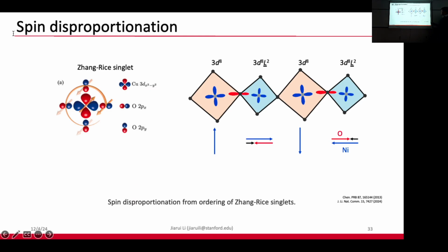So we try to recall a very old concept in cuprates called Zhang-Rice singlets. This is when you dope a cuprate. When you dope a cuprate, the doped holes exist in the oxygen orbitals, but they surround one copper site. So the copper site has a spin 1/2, and this doped oxygen hole also has spin 1/2, and they form a singlet to cancel out the spin on a single site.